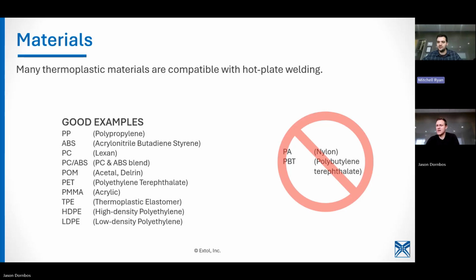Max says, why does the welding surface amount affect the cycle time when all the surfaces are contacting the heat plate at the same time? That's great. The way you're phrasing the question wouldn't be an issue. But typically with the larger parts, there is an amount of warp that you have to take out of the part and plane even. So if your parts are coming in perfect every time, then you'd probably have the same cycle time as the smaller parts. But typically there's an amount of time that's needed to plane the surfaces even and then heat the weld rib up.